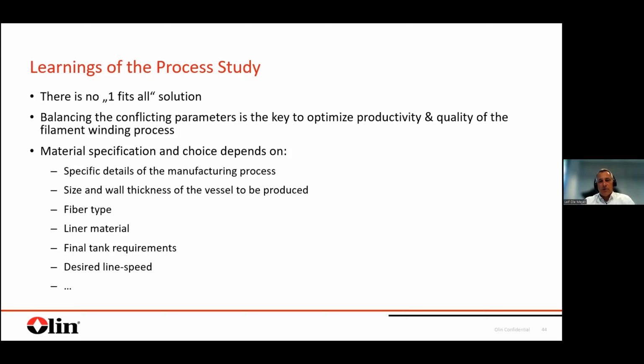Can you handle a small bath volume so that you are able to process higher reactive systems? Or do you need to have really a fully latent system so that you can run a very big bath? It's about the size and the wall thickness of the vessels to be produced. Yeah, a very thick wall thickness is always more prone to have effects of higher exotherm. The fiber type is basically critical. It's the wetting behavior. The liner material is critical because it's limiting your maximum allowable temperature during the tank. Then, of course, the final tank requirements, desired line speed, so productivity, and so on and so on. So overall, we have a lot of parameters that we need to balance and where we need to find the right way.